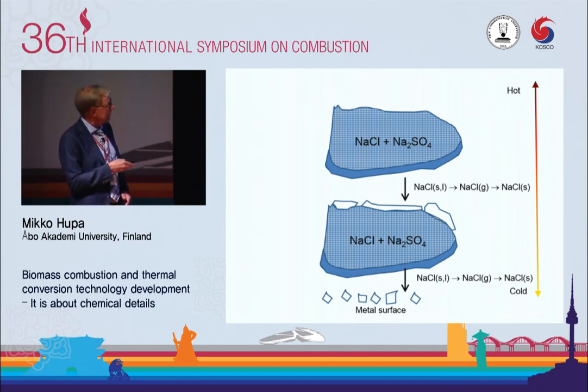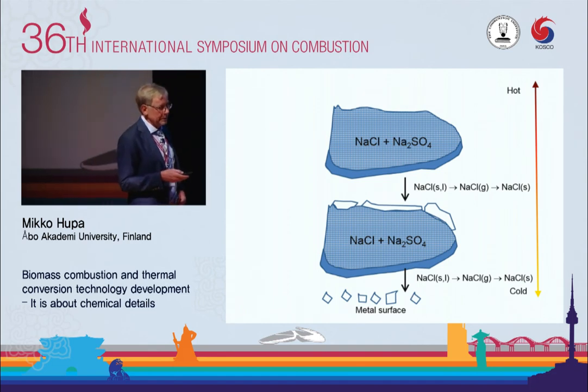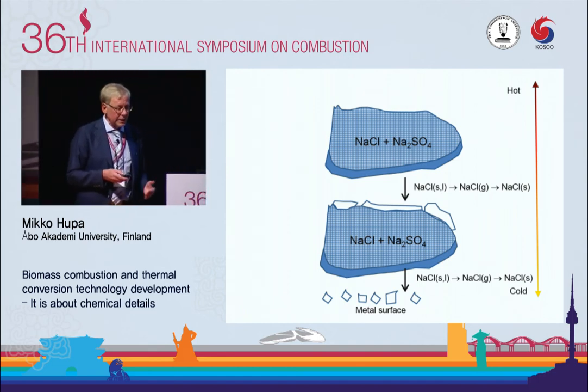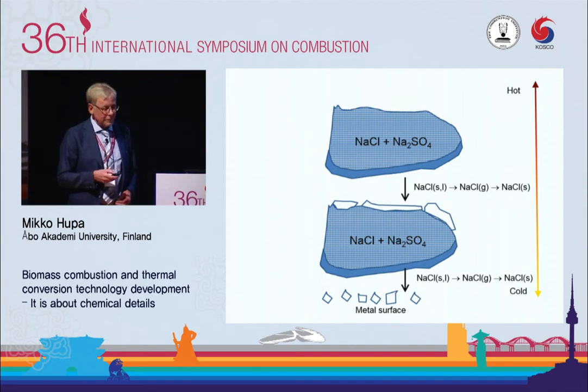And the consequence of this is that sodium chloride will partly go all the way to the steel surface, depending on the temperature conditions, and can enrich high amounts of this, even from small amounts of chloride. So this is something we want to study more.